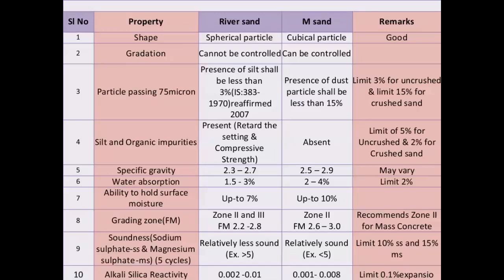And the one advantage of having M sand is that because of the cubical particles, it has very good interlocking and particle packing property, which improves the strength of the concrete. The only thing is the workability of the concrete is reduced significantly, so for that we can use some superplasticizers to improve the workability. When you see the workability and its retention, for river sand it is very good, whereas in M sand it is somewhat less. For that we have to control the fines and apply water absorption correction and use plasticizers. For setting, it is normal, whereas in M sand it is faster.